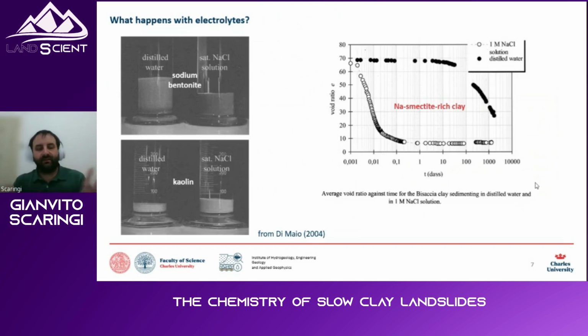I find these are publications from Professor Di Maio from my institution in Italy, about 20 years old. On the left, you see sedimentation tests. So what she did is basically she put a spoon of dry clay in a cylinder with about 1 liter of water, and mixed it to produce a suspension, and then let it settle down over time. And she noticed that depending on whether she had pure water, distilled water, or a concentrated sodium chloride solution,